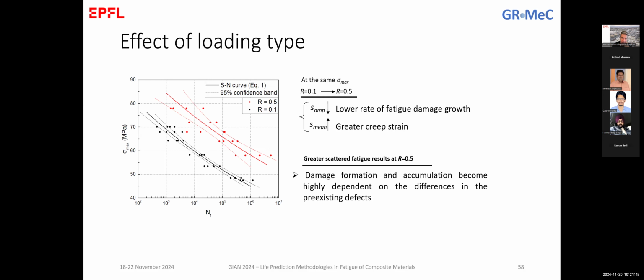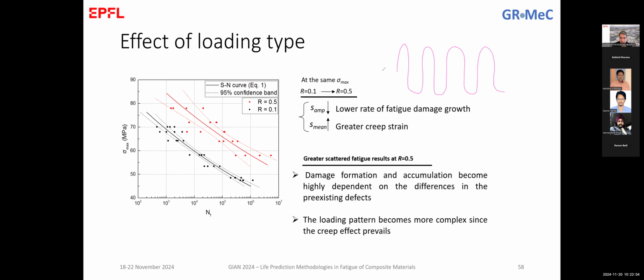And this is probably related to the maximum, so if I plot here, and start also this discussion about the creep effect that we'll see later on. If this is 0.1 testing, stress over number of cycles, 0.5 for the same stress max. So to compare these two stress levels, for the same stress max, your test for 0.5 might be something like that.